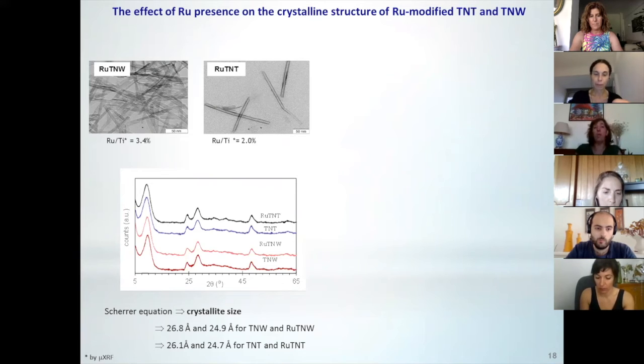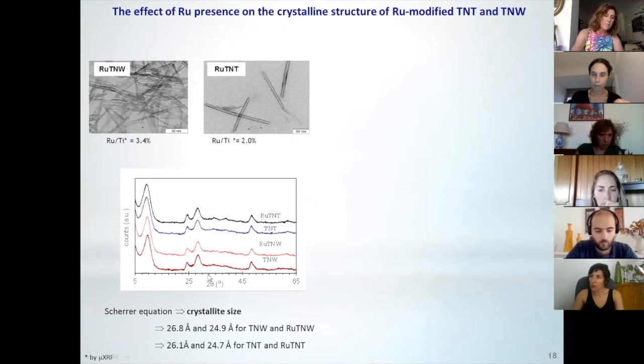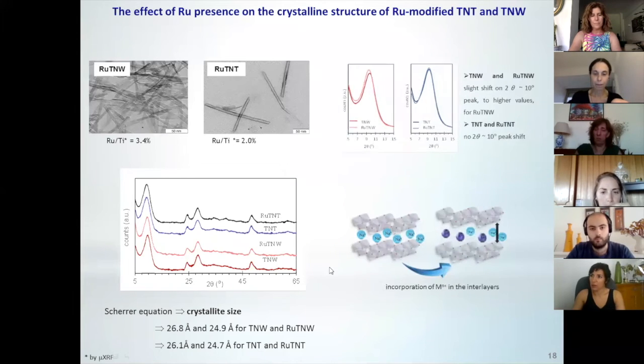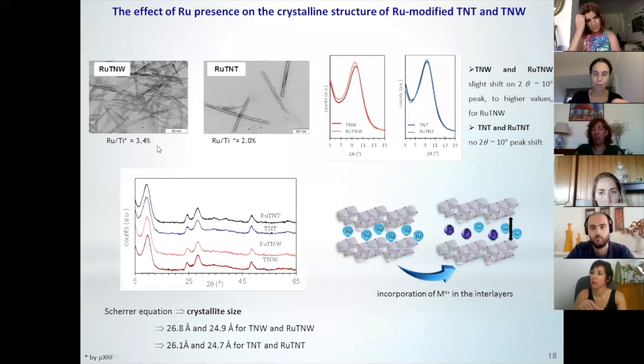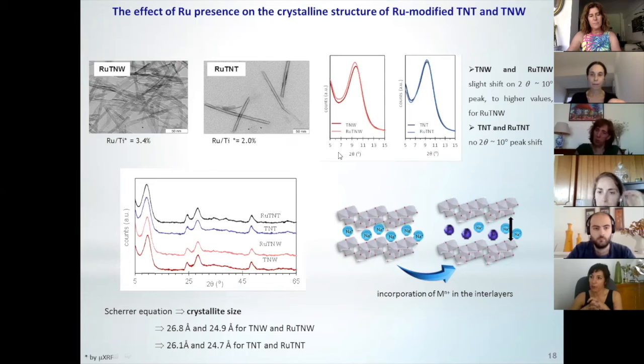We know that we can have ruthenium in the interlayers, or we can have it replacing the titanium. Okay, so the first thing that we must do is an XRD analysis. If we look here, well, it seems always in the same position, but this is not true. Remember that we have very, very small amounts of ruthenium. And if we perform the same analysis, but with more time, we can see that, in fact, for titanate nanowires, we have a slight shift in this peak here, saying that something happens in the interlayers.